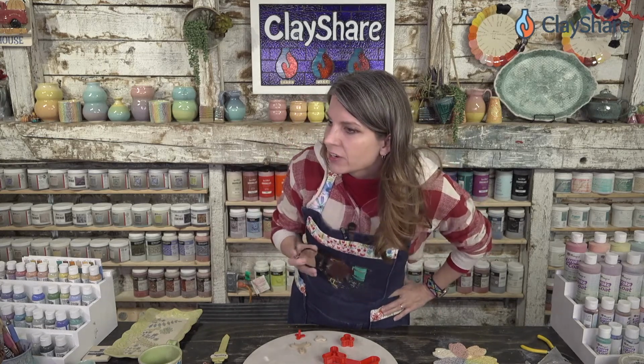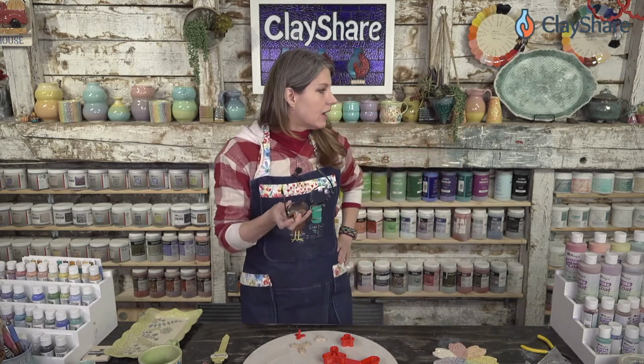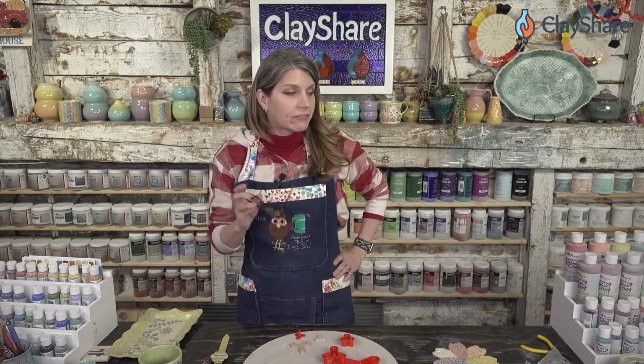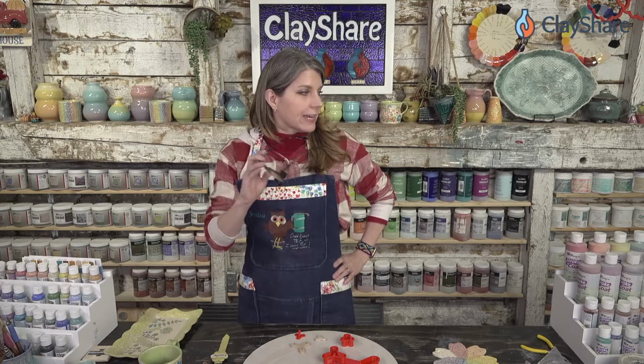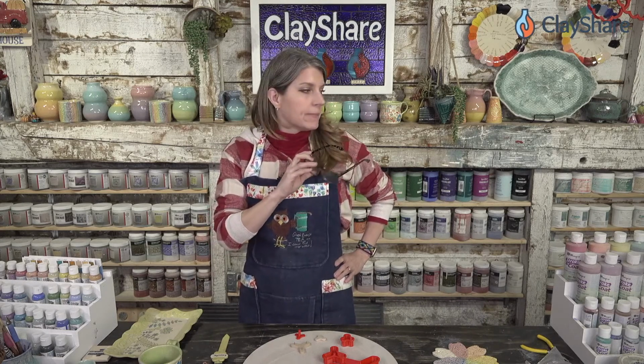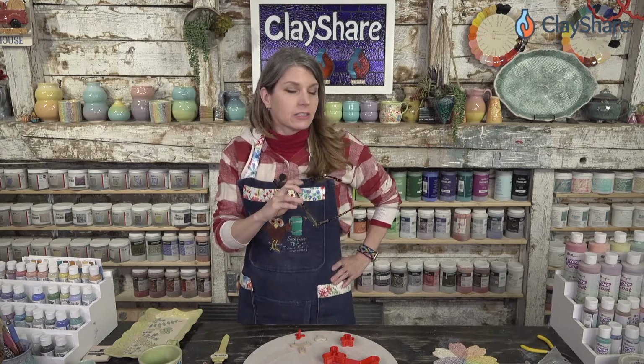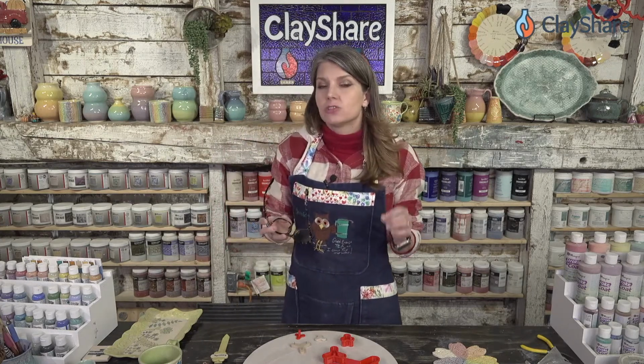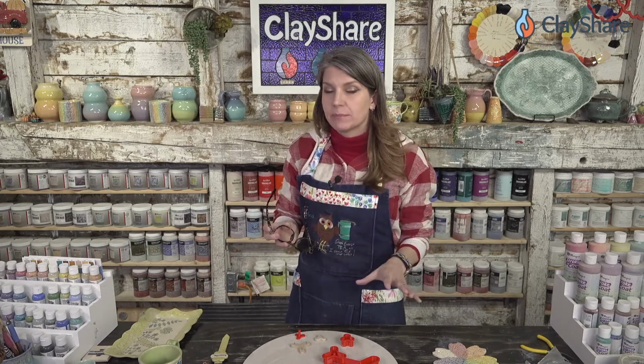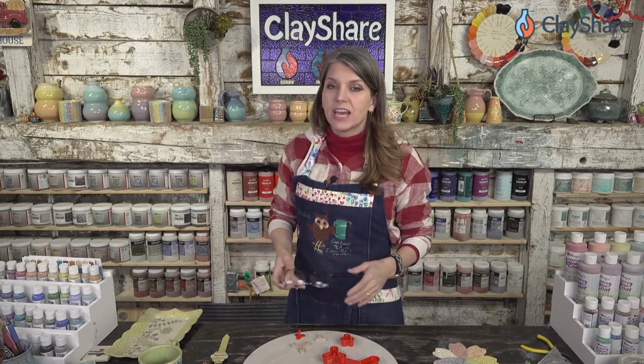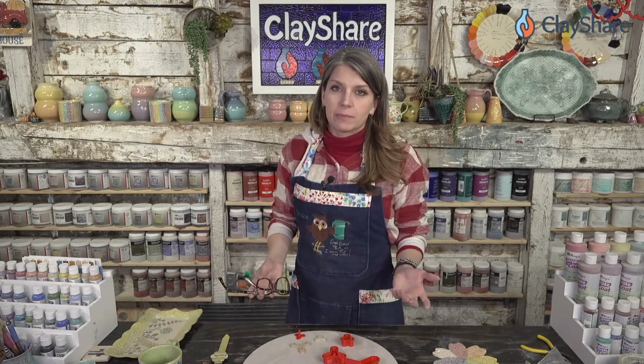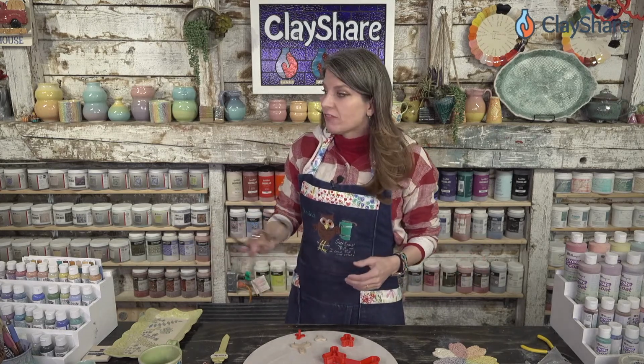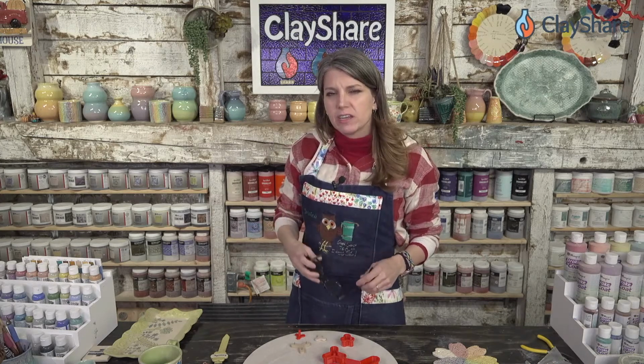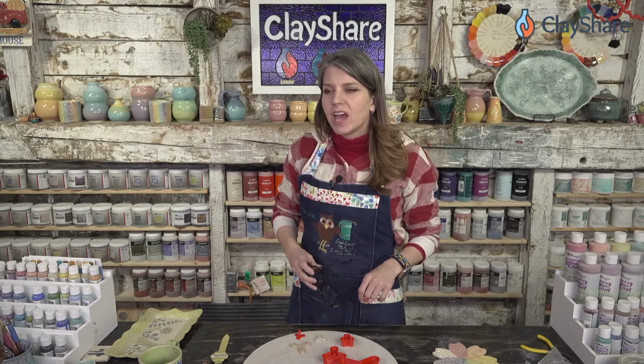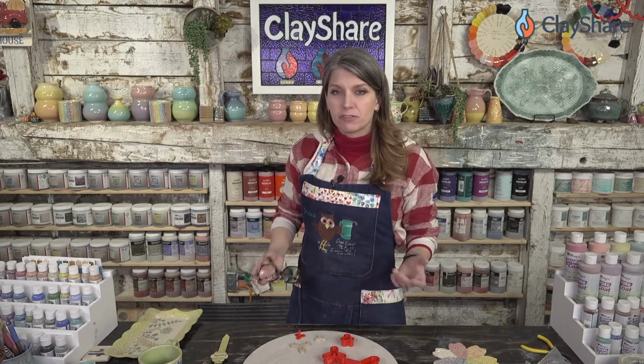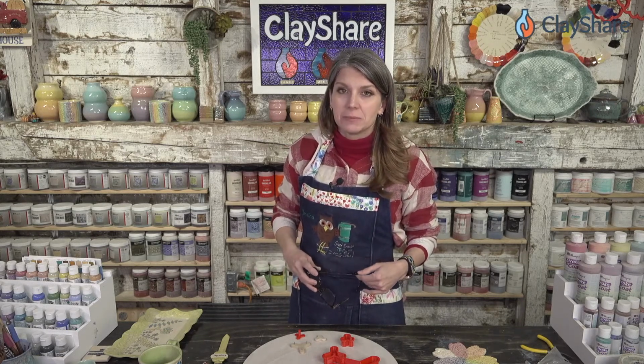I fired a pie plate again at cone 05 that I had fired to cone 5, and the color shifted majorly and it crazed. So some glazes do not like to be fired again at low fire temperatures. So keep that in mind and make sure you do tests, because you won't know what's going to happen until you do it. I think I've shared that pie plate in our Prime group and with our premium members. It was a bit disappointing because Jeff from GR Pottery Forms made the pie plate and gave it to me to glaze.